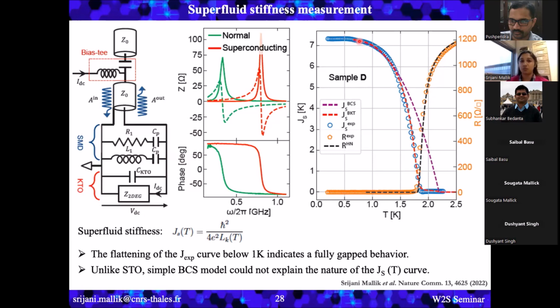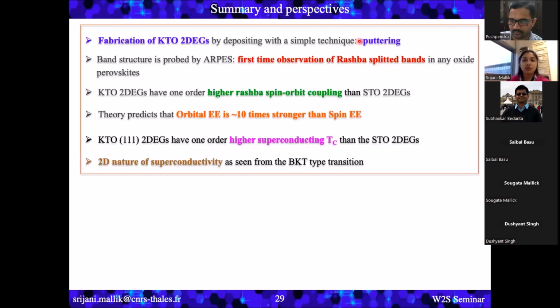With this, I would like to summarize my talk by telling that I think I could convince you that KTO 2DEGs are really promising systems to study the spin-to-charge interconversion and superconductivity. So in our case, with a very simple technique, sputtering, we could fabricate the KTO 2DEGs. Then we could also probe the band structure using ARPES, which was the first-time observation of Rashba split bands. And then we experimentally calculated the Rashba coefficient, which is one order higher in magnitude than the STO 2DEGs.